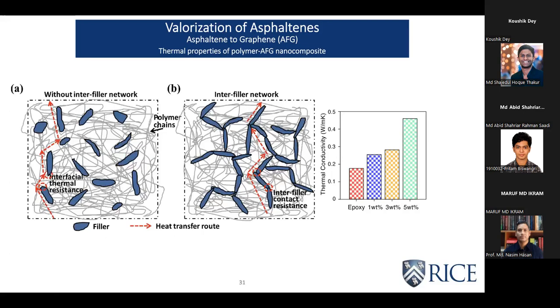And this happens because when you have a low graphene content, they are not connected with each other, but with increasing graphene content, you have an interconnected network of graphene within the polymer composite, and that gives a better phonon conduction path from one side to the other side, and you end up with good thermally conductive composites.